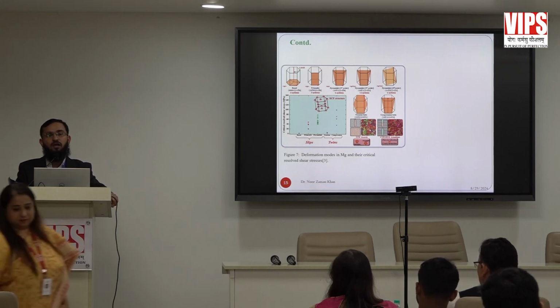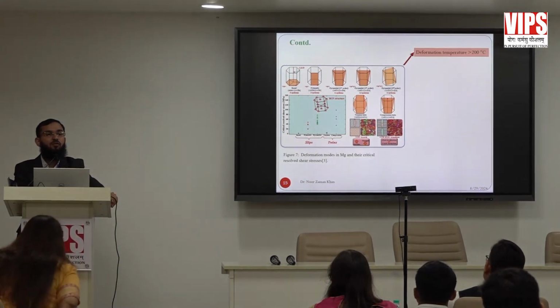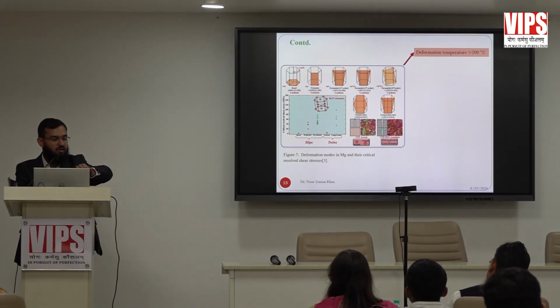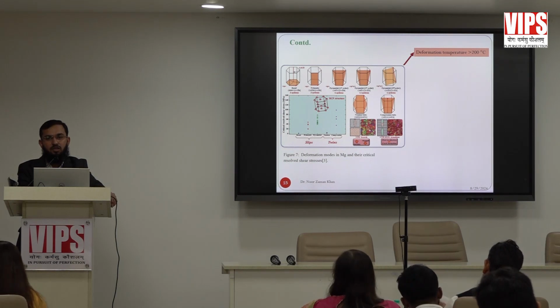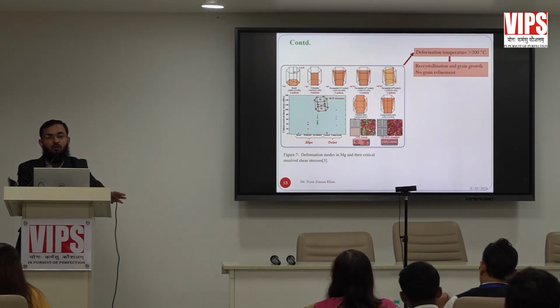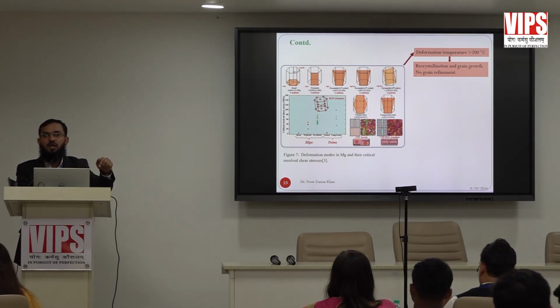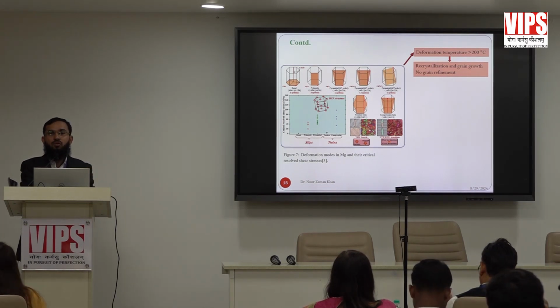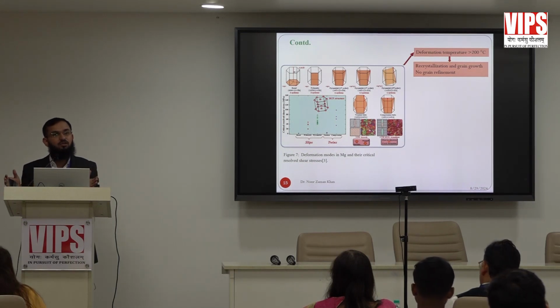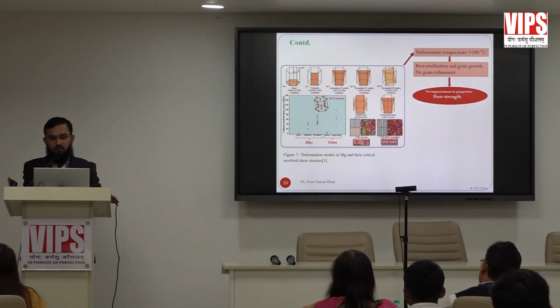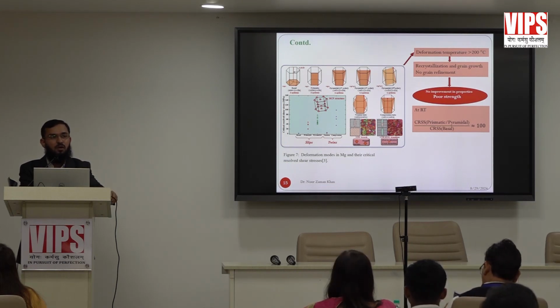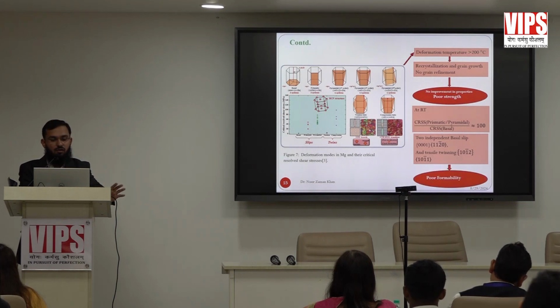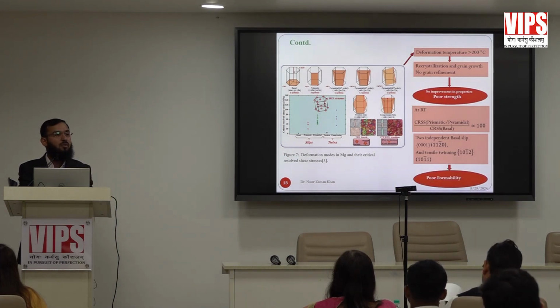So the target is how to activate all slip systems. If you want to activate slip systems, you have to increase the temperature. It should be more than 200 degree centigrade. Now what's the problem? If we increase the temperature of magnesium above 200 degree centigrade, it will lead to grain growth. And if you have ever heard about the Hall-Petch relationship, if the grain size is larger, it will reduce the hardness and strength. Due to grain growth, grain size will increase, and it will decrease the mechanical properties. So on one side you are activating the slip system, on the other hand you are reducing the strength. But we require to enhance both the strength, ductility, and deformation. So it will lead to poor strength. There is also a term, critical resolved shear stress. Ultimately, magnesium has poor strength and poor formability even after alloying.